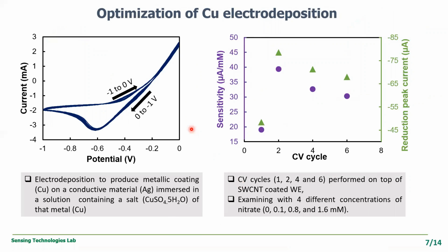And this is the optimization of copper electrodeposition. Here, the electrodeposition technique was used for this copper nanocluster formation. Electrodeposition is to produce a metallic coating, as for example here copper, on a conductive material, that is silver. The electrode is the conductive material here, which should be immersed in a salt solution. We have used copper sulfate salt solution here. This electrodeposition can be performed with cyclic voltammetry by applying a potential range from 0 to -1 volt, and the copper is deposited especially at -0.6 volt.